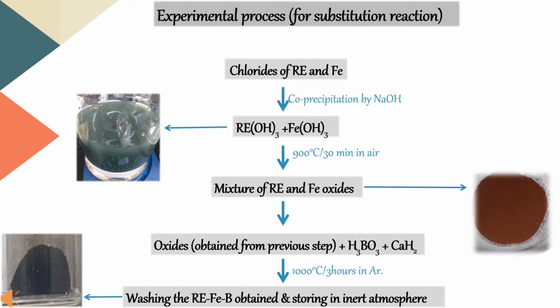Sodium hydroxide, 3 molar, was used as a co-precipitating agent, and the hydroxides obtained by this process were converted to the oxides by annealing the hydroxides at 900 degrees Celsius for 30 minutes. The mixture of oxides obtained was mixed with boric acid and calcium hydride, and a reduction diffusion reaction was carried out in the tube furnace. This reduction diffusion reaction happened at 1000 degrees Celsius and took almost 3 hours in an argon atmosphere. By this process, the ReFeB magnetic particles were obtained, and some calcium oxide was also mixed with these particles. This extra calcium oxide was removed by washing with water.